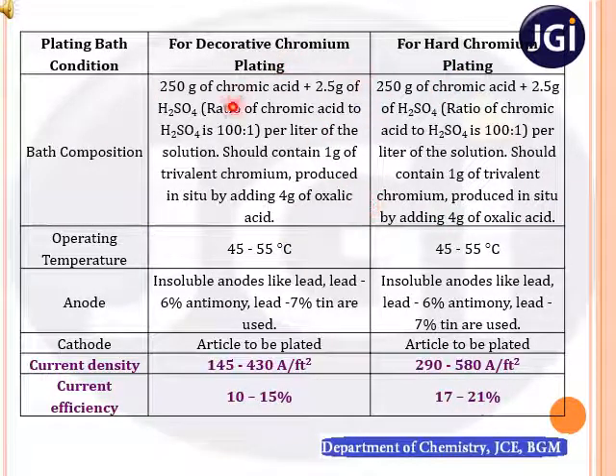Right. So the next part is operating temperature. The process will be carried out in the temperature range of 45 degrees centigrade to 55 degrees centigrade. As I said, we are using an inert electrode or insoluble anode. For example, we can take lead metal directly, or a mixture of lead and antimony, or lead and tin, as anodes for the electroplating of chromium. And we know that the cathode is the article which is to be plated.